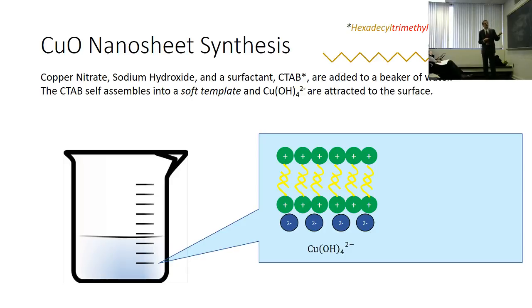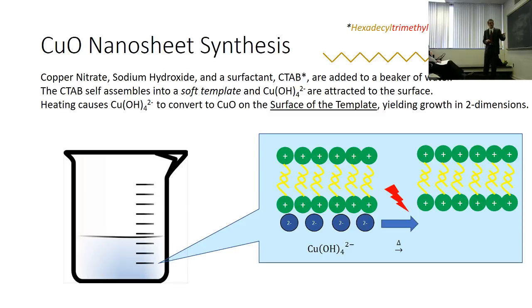This is where the base comes in, sodium hydroxide. When you have copper in a basic environment, it forms a hydroxide intermediate, copper hydroxide, negatively charged, good. It attracts to the positively charged surface, and since you're attracted there, that's where the reaction occurs when you oxidize it. When you heat it up, you restrict the growth in one dimension, so growth occurs in two dimensions, and you get a nanosheet.